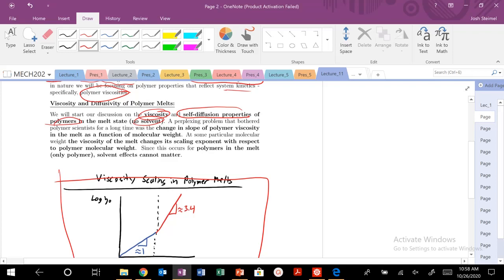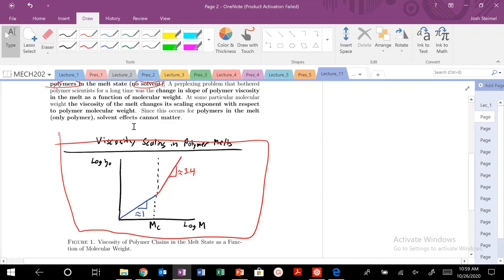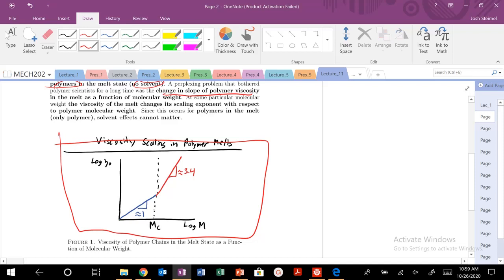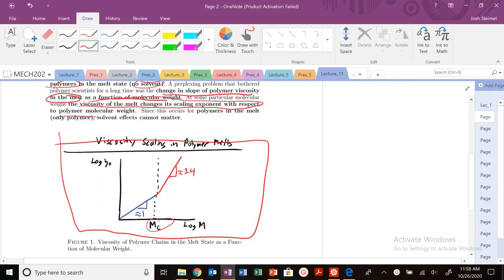Let's focus on viscosity and self-diffusion of polymers in the melt state — no solvent. Experimentally, for many years, we were able to reproduce this curve — figure one — for many different types of polymer melts. We saw this change in slope of the polymer viscosity in the melt state as a function of molecular weight. At some critical molecular weight or entanglement molecular weight, the scaling exponent changes. We see a change in scaling from viscosity scaling as M^1 to this very non-intuitive exponent of 3.4.